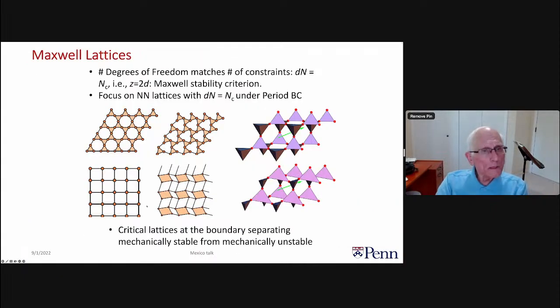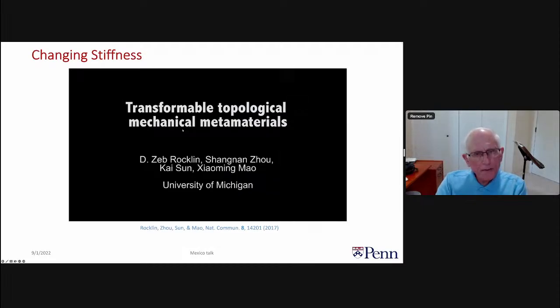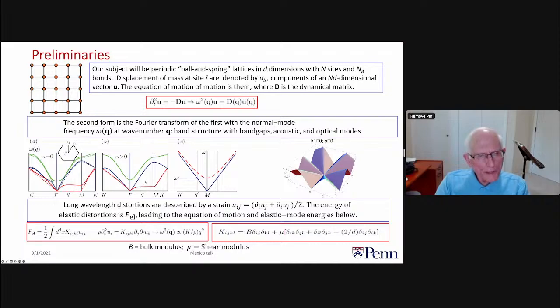So what I'm talking about is going from this lattice to this lattice. In the process, this lattice has the zero mode that runs from gamma to M, and this lattice loses that altogether. It's fully gapped. And if you just look at the straight green and blue and red lines here, the spectrum of this lattice, when I've turned on the next nearest neighbor forces, is qualitatively very similar to what happens when I twist the Kagome lattice through an angle alpha.